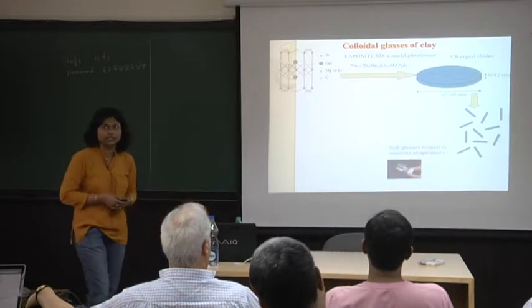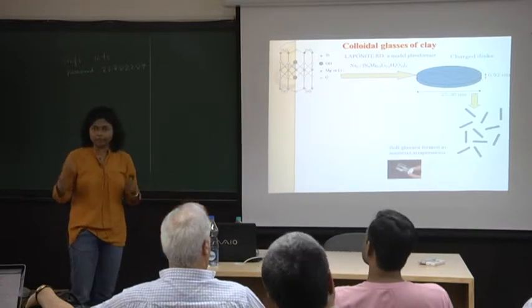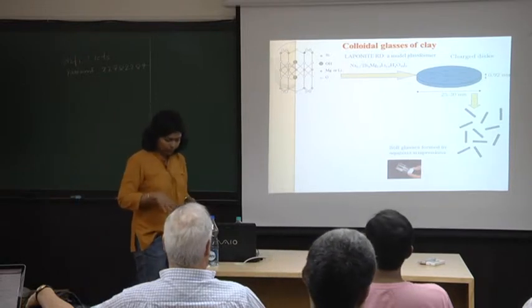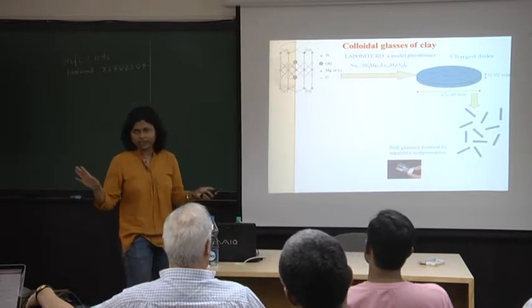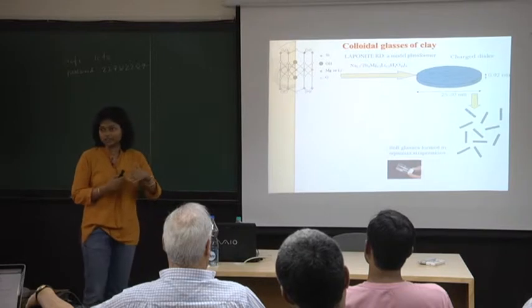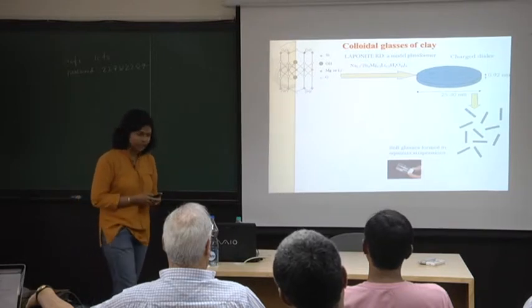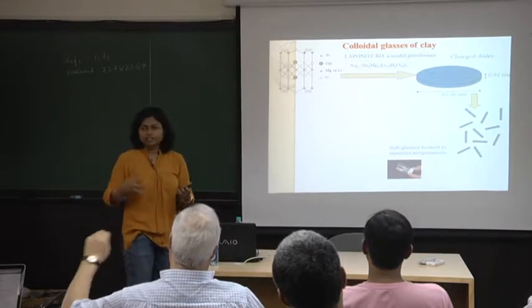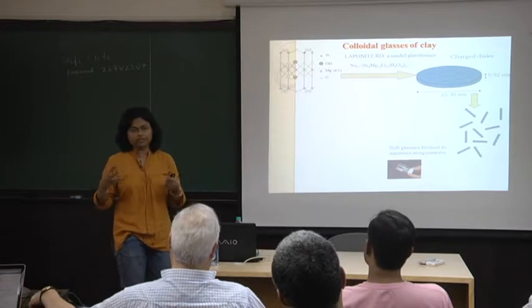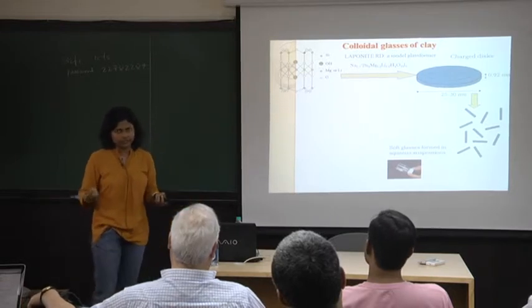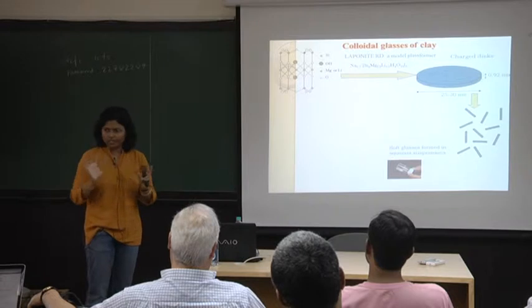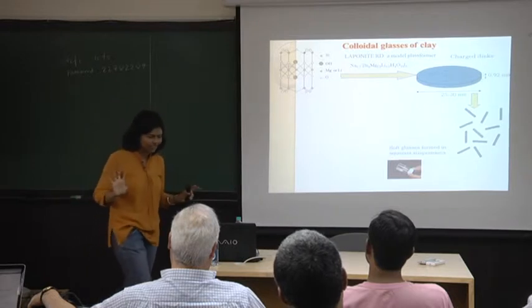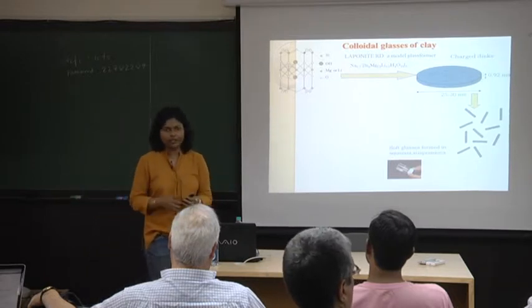So here's how we make our suspensions. We take powder, dissolve the powder in water, and shear or stir it very hard because there are clusters. You want to dissolve as many of these clusters as possible. Immediately after making the sample, it's maybe 10 times more viscous than water. You seal the whole container up, making sure nobody is fooling around with it.